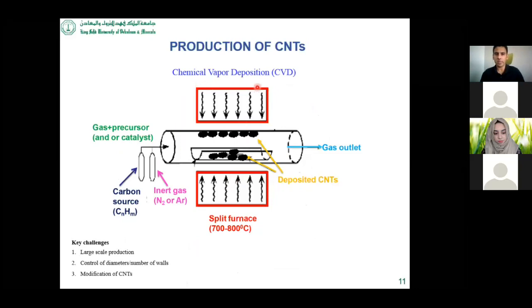One of the techniques is chemical vapor deposition, which can be used to produce a comparatively large amount of CNTs, or carbon nanotubes. Here we basically use a carbon source and heat it at high temperature. It decomposes in the presence of a catalyst, which of course is very important. So decomposition occurs, and the carbon nanotubes are produced.